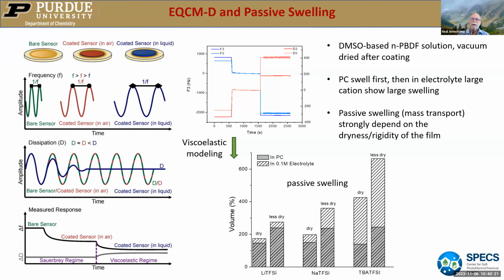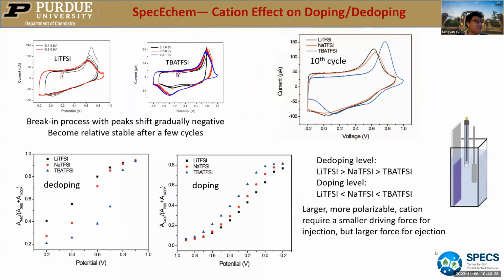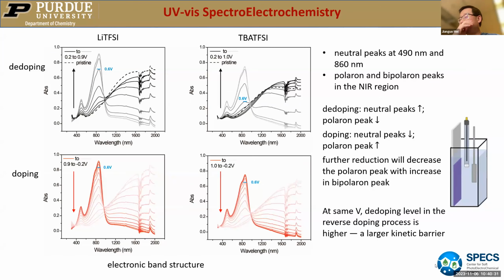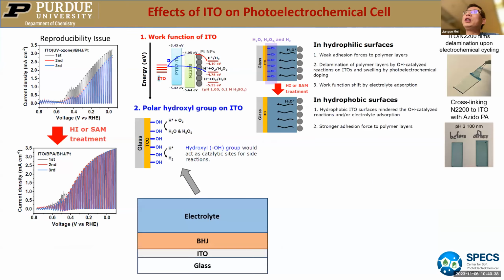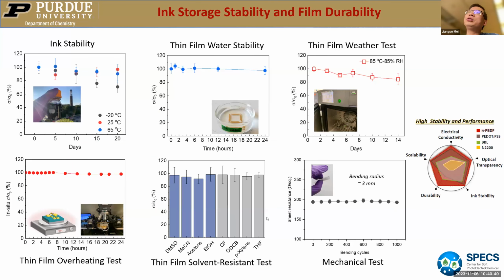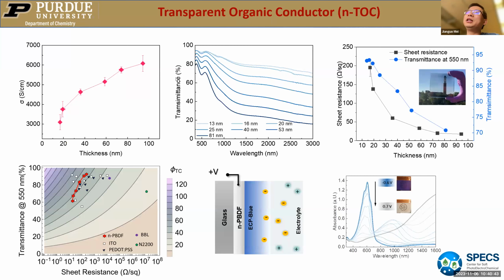Is it truly transparent in the visible though, because of the polaron absorption? I can say it's transmissive. The transparency is thickness dependent, obviously, and for it being a conductor, if you use somewhere about 40 nanometers, you would have transparency around 80% in the visible range. Okay. All right. Interesting.